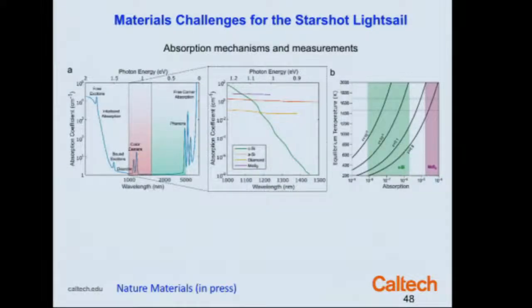Okay, what about the actual physical characteristics from an optical sense of the materials? All the materials we're talking about are dielectric materials. They have wide energy gaps. Therefore, they have absorption at short wavelengths. They have coupling between the optical phonons and the lattice at long wavelengths, the so-called Reststrahlen band or phonon polariton modes. They also have defects that give rise to color centers that give the crystals physical color due to trap to band transitions. So these are the generic characteristics of these materials.